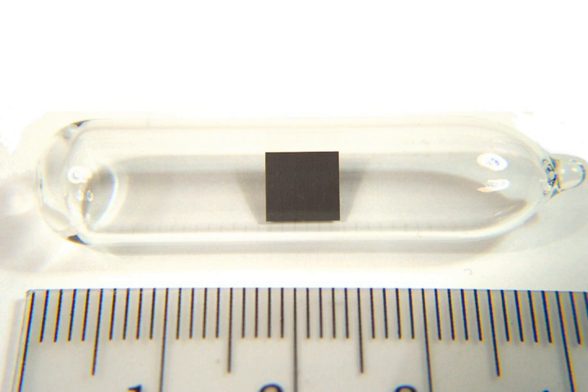For the primary deposits, the source pegmatites, which are usually obtained by mining, are divided into small parts and then undergo flotation. Alkaline earth metal carbonates may be removed after reaction with hydrogen chloride, then follow thickening, filtration, and calcination. The result is a concentrate with rare earth content of up to 90%. Secondary materials, such as coastal sands, undergo gravity separation. Magnetic separation follows, with a series of magnets of increasing strength. Monazite obtained by this method can be as pure as 98%.